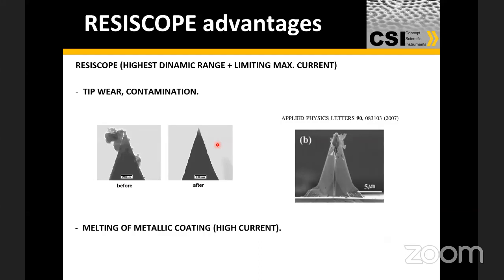So again, this is an interesting slide, because this shows some of the classical problems that you face. If you look at the image on the left here, the conductive coating on the cantilever tip has actually worn off, precisely because of the problem that I alluded to in the previous slide. If you suddenly have a surface where you get a very high amount of current, and you're not able to regulate that current, you're going to end up burning your tip. The conductive coating is simply going to wear off, burn off, and that sort of thing.